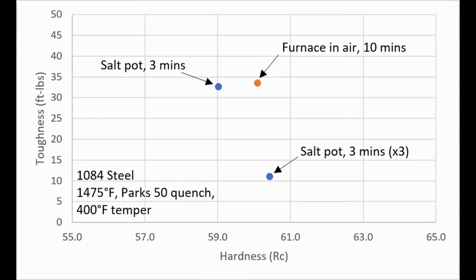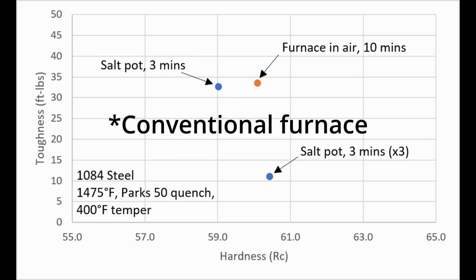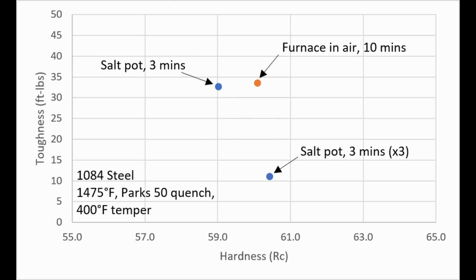For Knife Steel Nerds, I have tested heat treatment changes I was sure would improve the steel, but instead found worse properties. For example, I did a study on rapid heat treating with salt pots. When I did a rapid 3-minute salt pot austenitize on 1084, the properties were similar to the furnace, but they were a little softer with the same toughness. But I also tried a rapid triple quench. We would expect the grain size to be much finer and to improve toughness.